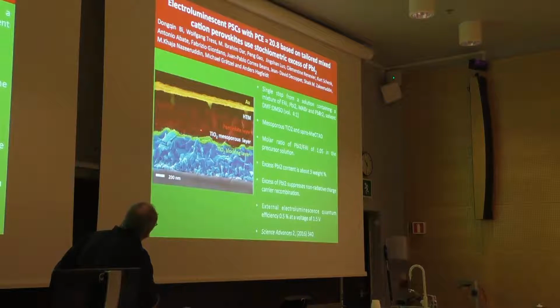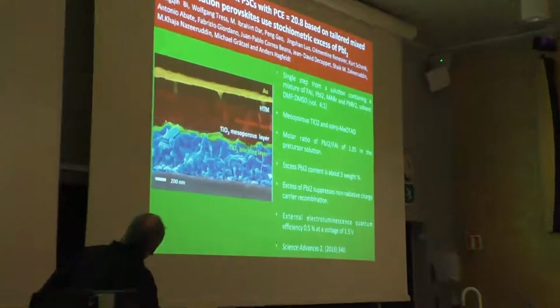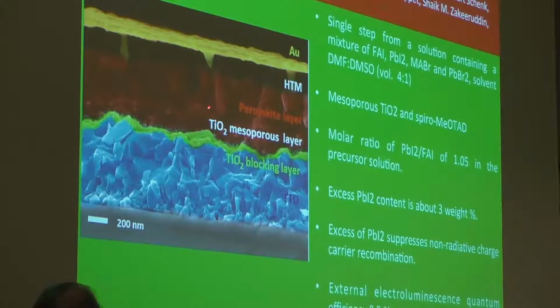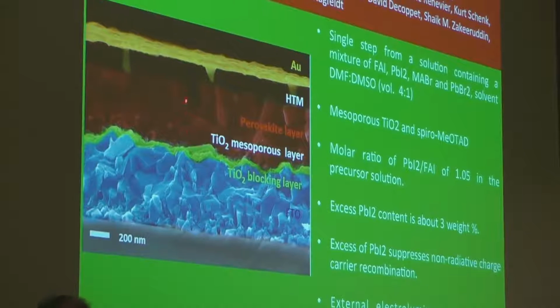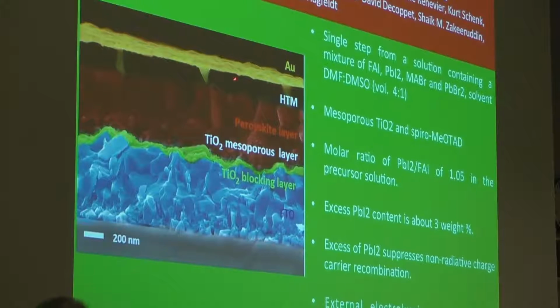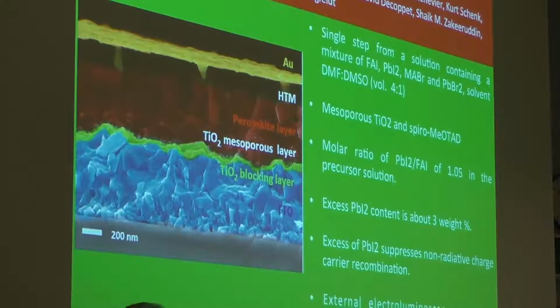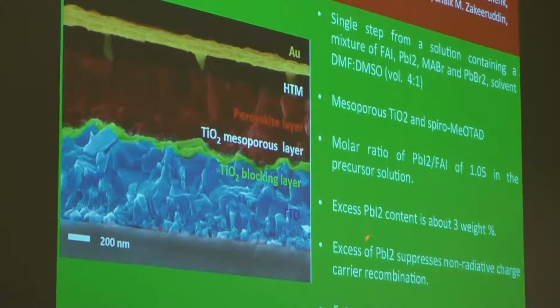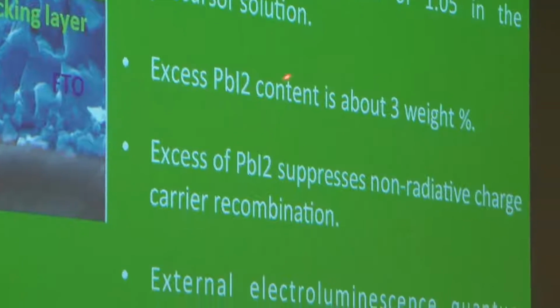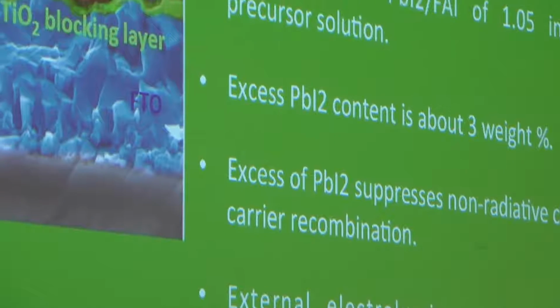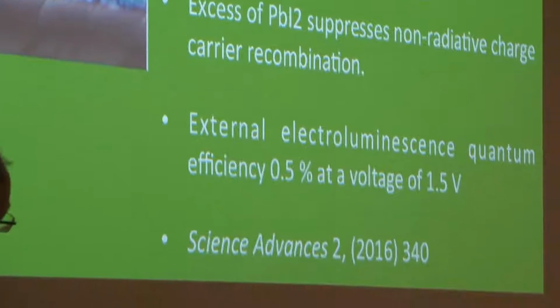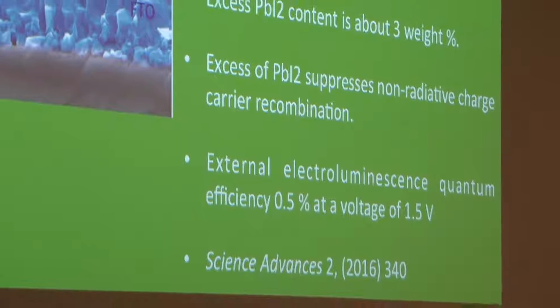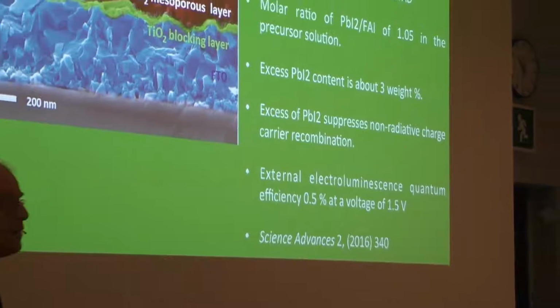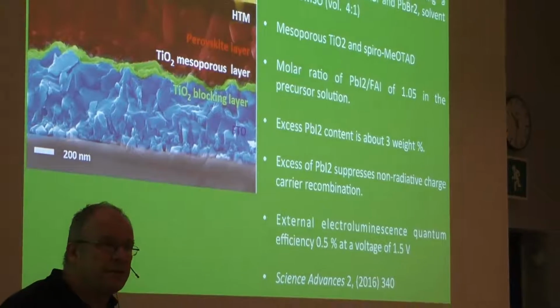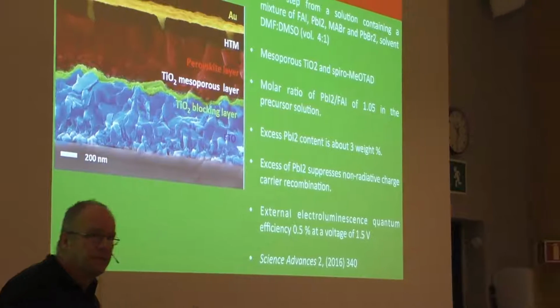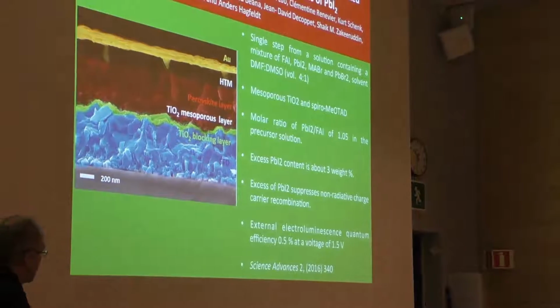What you can see from the SEM picture here is that it's a very thin layer of mesoporous TiO2, 100-200 nanometers. Most of the perovskite is a compact layer on top. We call it the capping layer, and then the hole transporting medium and gold as a contact. So here we optimized the mixed ratio. We saw that an excess of lead iodide was beneficial, passivating recombination, and besides having a nice efficiency, we also measured a very high electroluminescence, about 0.5% at the solar cell voltage. And this is very high. It is as good as the best silicon solar cell. A dye-sensitized cell is about 10 to the minus 6 in comparison. So this is a very high electroluminescence, and I will come back to that.